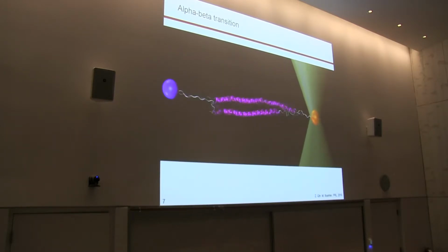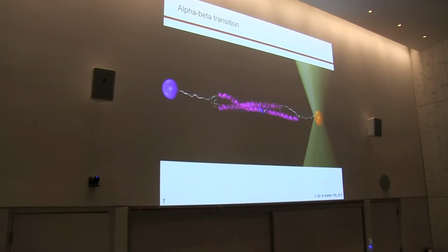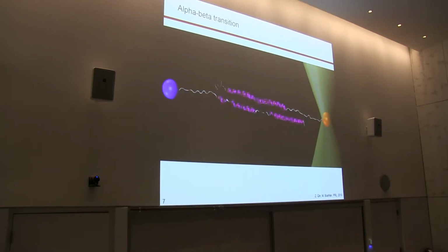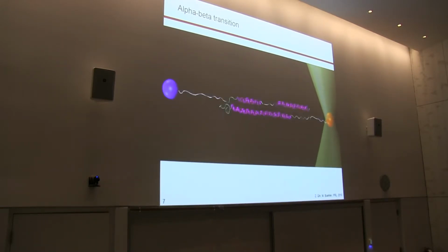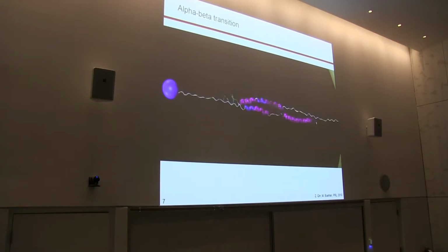And then I can see that those hydrogen bonds break apart to unfold the alpha helix structure during the deformation. At the same time, once the alpha helix gets unfolded, it also creates the possibility for those building blocks to form new hydrogen bonds with their neighbors.